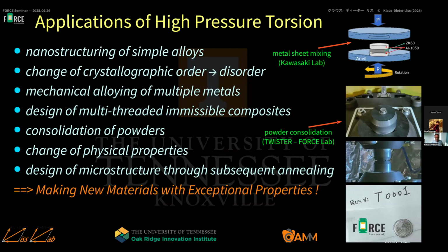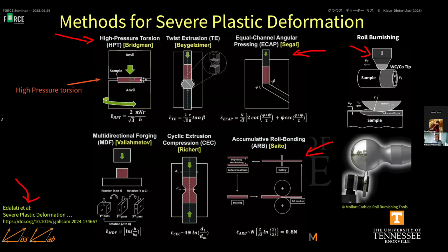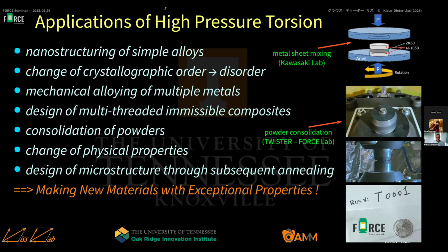Okay. Yeah, number 1 in that paper, if you remember the slide, is high pressure torsion, because high pressure torsion gives you very severe plastic deformation, a lot of strain, a lot of plastic strain. So applications of high pressure torsion are in the nanostructuring of simple alloys, so aluminum, magnesium, steel, and so on. And it can change the crystallographic order to disorder. We have studied that, for example, on titanium aluminide, which are intermetallics, and they disorder at high pressure torsion with severe plastic deformation. And this may be interesting even to study other phenomena like radiation damage, where you have an order to disorder transition due to severe or extreme environments.